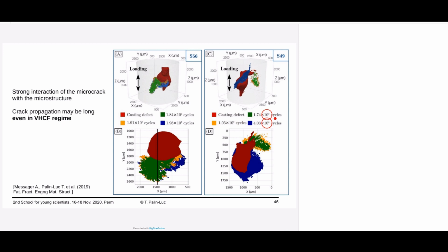This is the case here. You can see here that we go from 1 10^7 up to 4 10^8. So here there is an enormous factor, a factor of 10, and there is no macroscopic crack, but there is a crack which is practically blocked. Here you see the green one and the orange one with a very, very small propagation, but only this crack propagates at the end. So this is very important because in the literature, many people consider that the crack propagation is negligible in the gigacycle fatigue regime, and these experiments show the opposite.